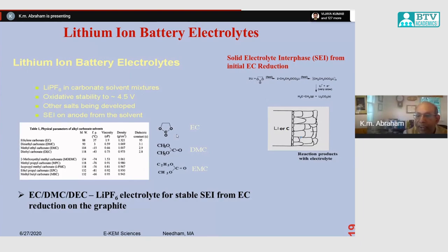So the first reduction, when you charge your battery, is done in the factory. The ethylene carbonate is reduced to form a lithiated organic carbonate material. That's an insoluble material that coats the graphite anode, and that is the SEI, the solid electrolyte interphase. So the use of ethylene carbonate is very important, but it's a high melting liquid.